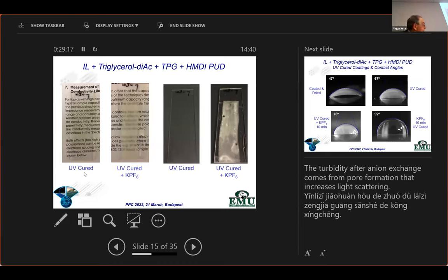Okay, so anyway, here I want to talk about the tripropylene glycol, because this is a UV polymerizable material. With these particular dispersions, because of thermodynamic stability, they can begin to dissolve if you add water. So having a chemical linking step may be required if you don't want your materials to wash away in the rain.